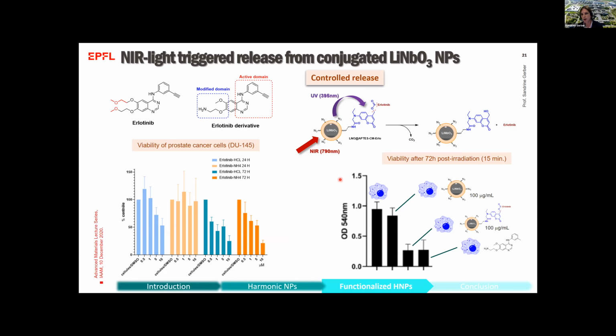So then we moved on with the controlled release by irradiation of the conjugated nanoparticles at 790 nanometer, and we measured the viability of the cells 72 hours post-irradiation. The irradiation time was kept at 15 minutes.